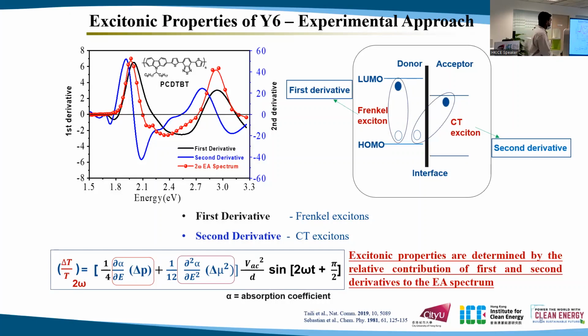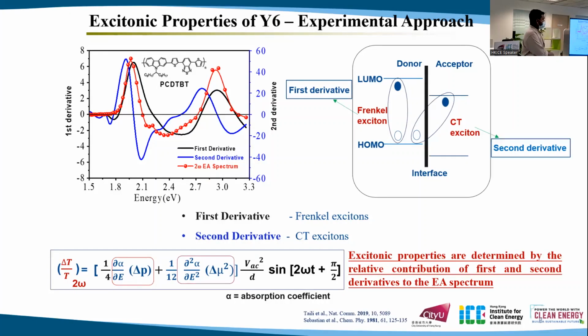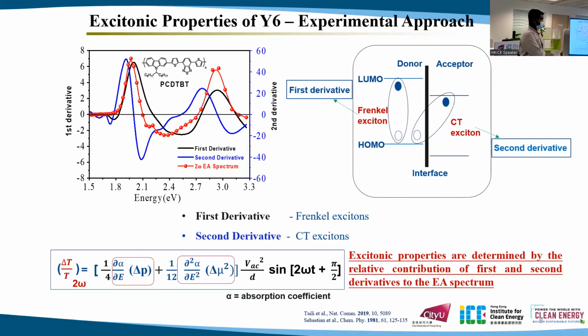And we can see this example. This red curve shows the second harmonic EA spectra of PCDTBT, and it matches more to the black curve. That indicates that PCDTBT has more Frenkel excitons. And this is the equation of the EA spectra that we have derived.